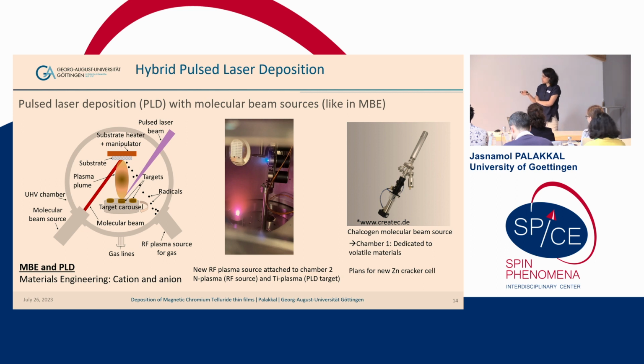And in addition to this, we also have a radio frequency plasma source for gases in our hybrid PLD system, because this type of plasma source is usually attached to an MBE where you need to grow nitrides. In the case of a PLD, you can already supply the nitrogen inside the PLD target. But if you want to grow oxynitride or a nitrogen and tellurium mixture, you have to go for such a technique. And we already implemented the plasma source, and this is being attached, and currently we are growing chromium tellurides in this chamber.